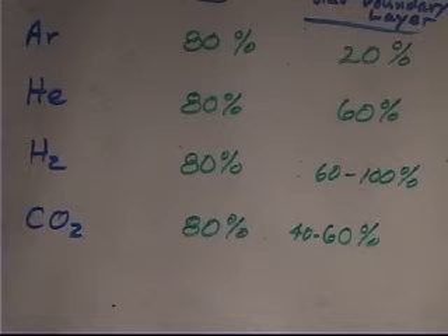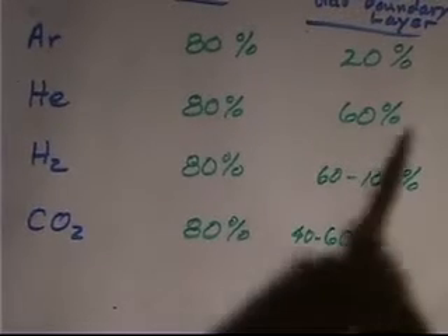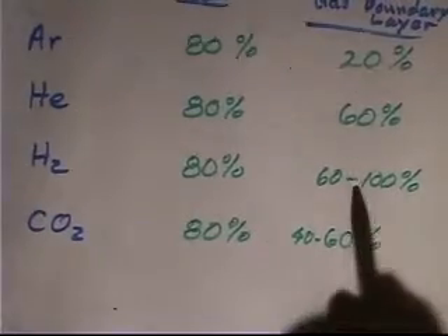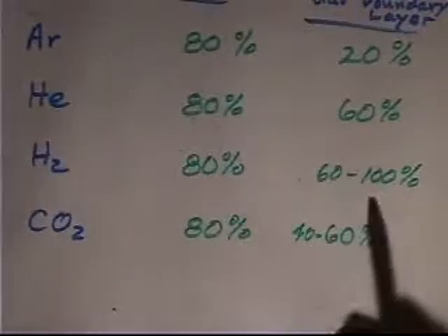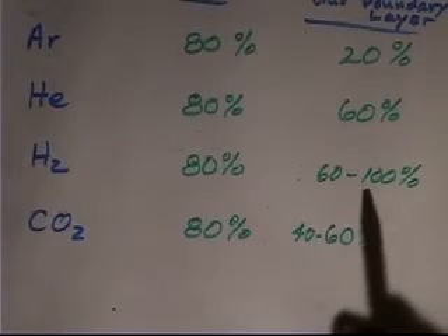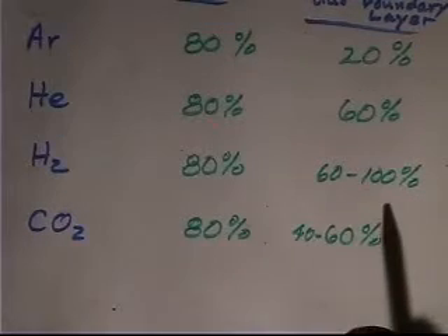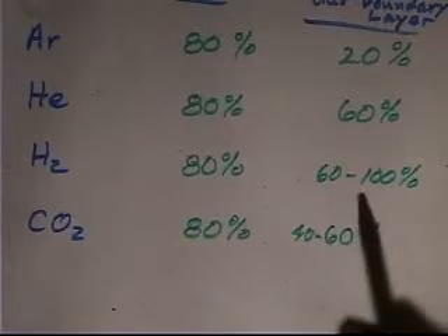The only problem with that is if you didn't handle it quite right and you're igniting hydrogen and doing this in air, there were a few people who blew themselves up. So the atomic hydrogen torch, which is what it was called, which was just 2 electrodes designed to shoot a hot flame at the weld pool, was used. Another problem is you can't use hydrogen on steels, on carbon steels, because you get hydrogen cracking. Who wants to weld in a 100% hydrogen atmosphere?